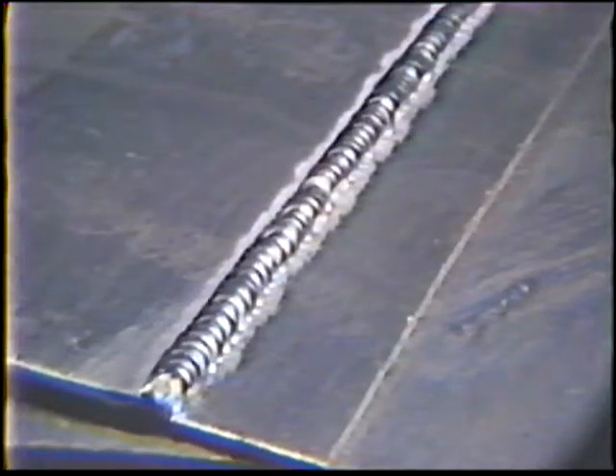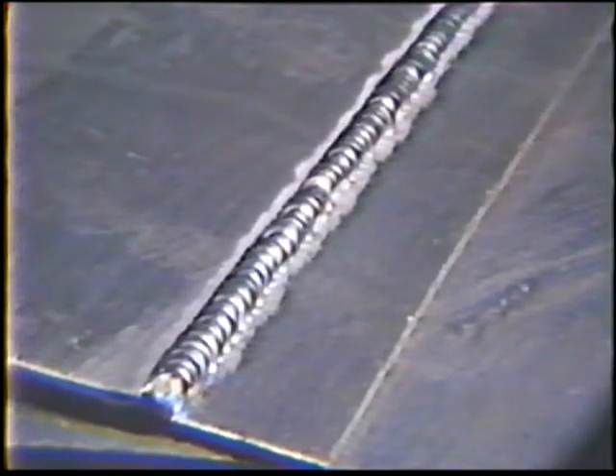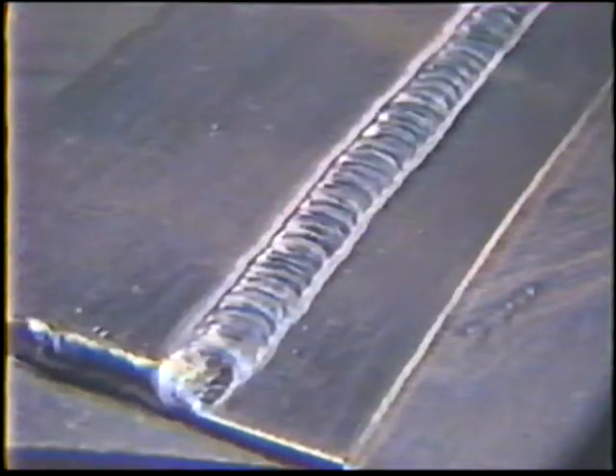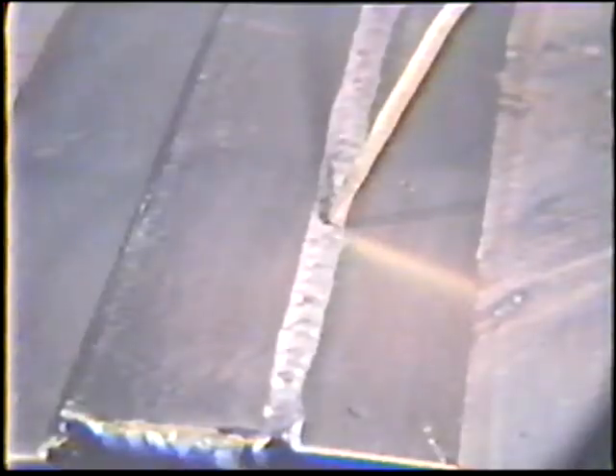The finished bead face should be 3 electrode diameters wide, slightly convex, and have an even ripple. Too low a current or too fast a travel speed will produce an excessively convex bead face with poor fusion into the base metal. Too slow a travel speed or too high a current will produce a concave weld bead with excessive penetration and blistering.